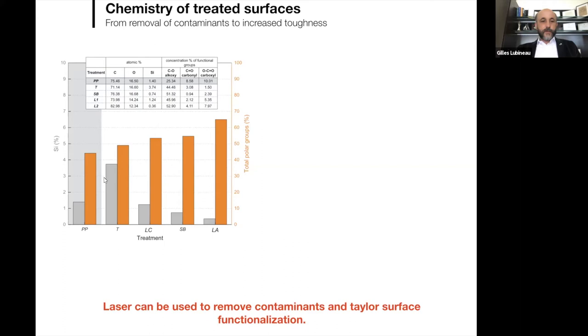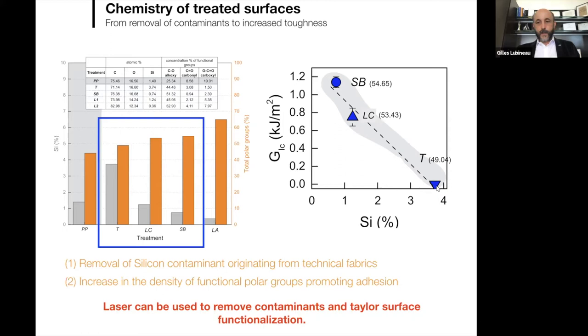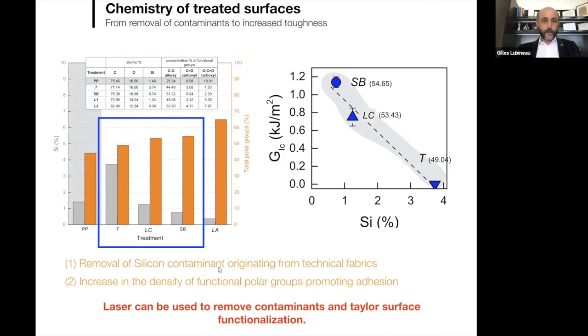Another classical effect of laser treatment is modification of surface functionality — introducing more polar groups on the surface, which promotes adhesion. At the same time, you clean the surface. The gray bars show the level of contaminants: laser treatment reduces silicon content significantly, which is known to be a contaminant, since joint toughness is inversely proportional to contaminant content. Laser treatment can clean, polarize, and remove contaminants from your surface.